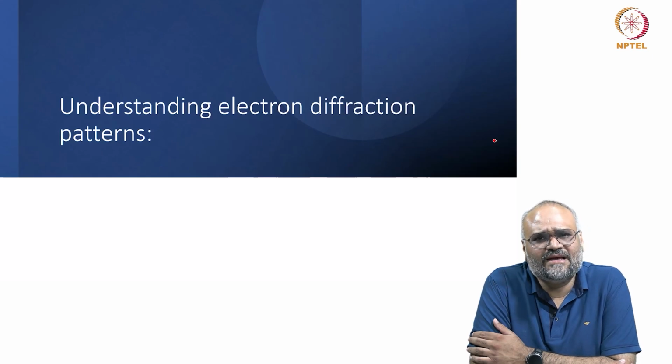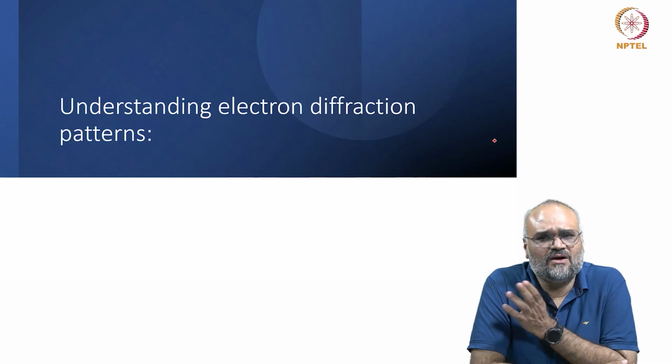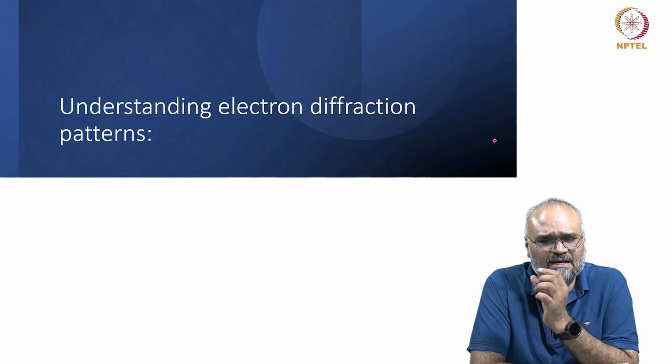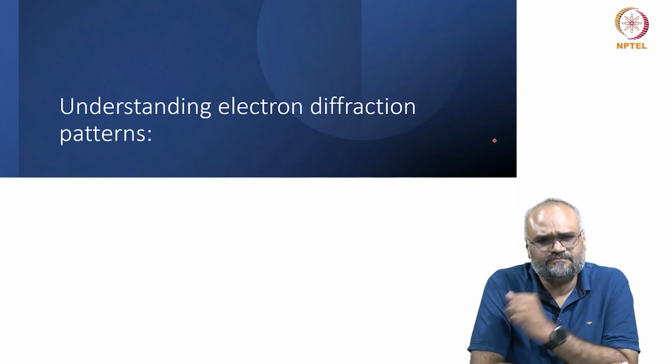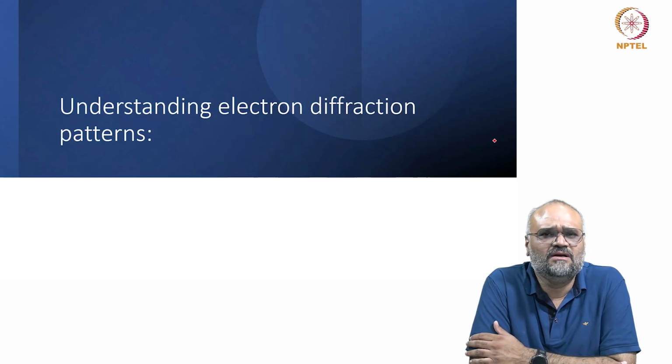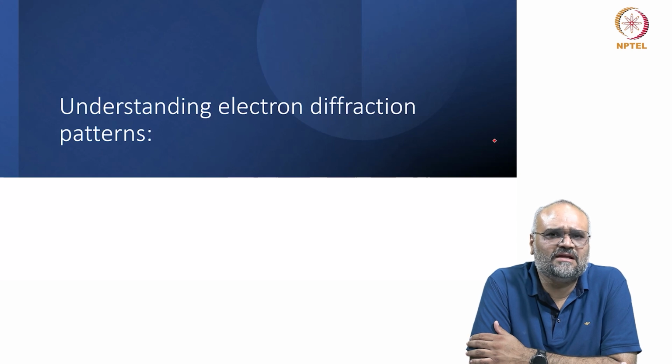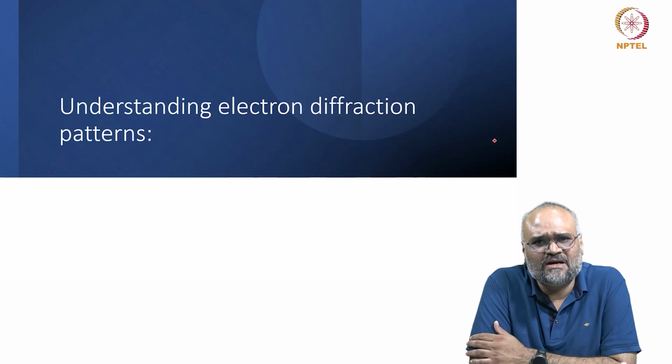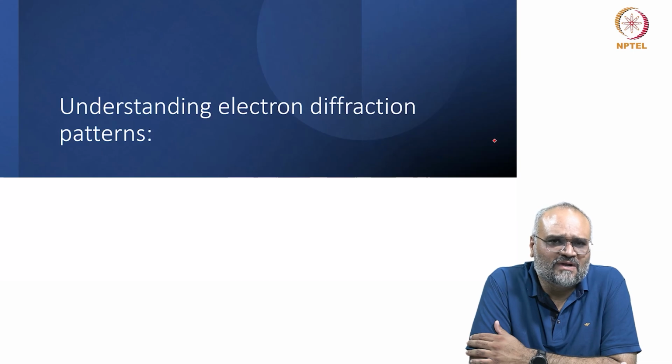Now, I've shown you the example of how the Kikuchi bands are used as a guideway or a highway along which you orient your specimen, and you let the Kikuchi node coincide with the bright spot to obtain a symmetric diffraction pattern. Once you get a symmetric diffraction pattern, based on some simple geometric relationships, let us try to index the reflections. Let us try to index the diffraction spots that you get on an electron diffraction pattern.